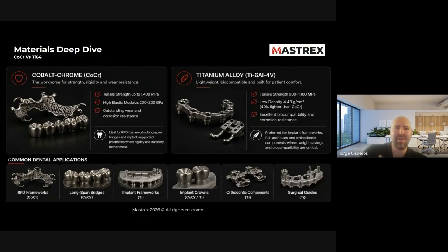Yeah, definitely. That's something I can talk about. As far as the material quality and particle size goes, that seems to be pretty industry set and standard. There's reasons for that. When spreading the powder, we have a recoater. When it lays a layer out, you have a feed system that's moving up, and then a recoater that pushes it over and spreads a thin layer. So in order for material to be spreadable, there's typical sizes that are used. It's typically from 15 to 53 micron particle size. So it's something you wouldn't have to worry about. That's just ordered. And that tends to be what the size is for both of these materials.